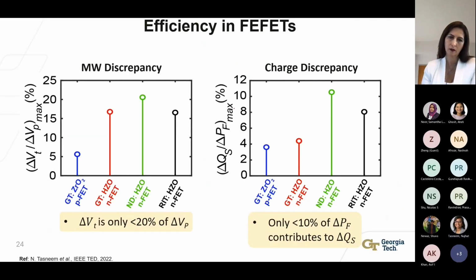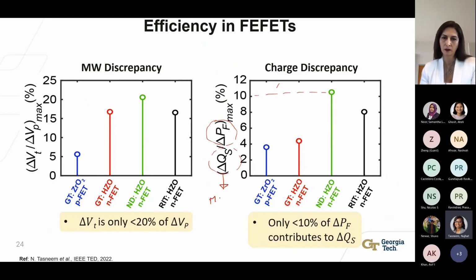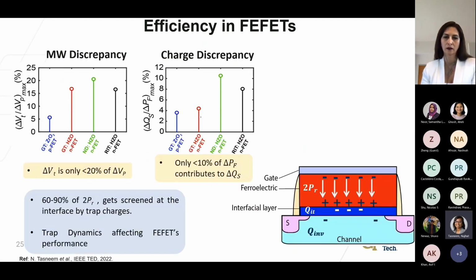So the second figure here shows that only a fraction of the ferroelectric charge, a maximum of 10%, contributes to the semiconductor channel charge, which in turn is responsible for the memory window. And this is why we have very low memory window efficiency, a maximum of 20% in FeFETs. So the results from this experiment indicate that only a fraction of the ferroelectric charge is getting electrostatically reflected in the semiconductor channel, while the majority of it, around 60 to 90%, is getting screened at the interface by trap charges.